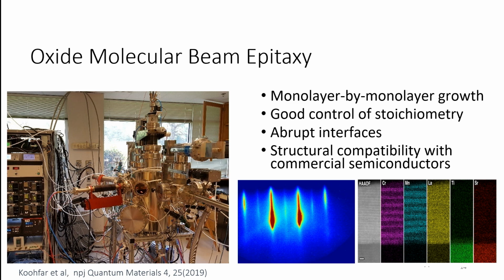And when we in the MBE field say we're growing thin films, we're thinking of films which are only a few nanometers thick. In some other fields, a thin film is a few microns thick. And that would take a couple of hours for us to get to those thicknesses. Right, but the cool thing about being able to grow at these really slow rates is that we have really good control of the defects in these systems. So we can grow films which are really atomically precise with really low defect densities.